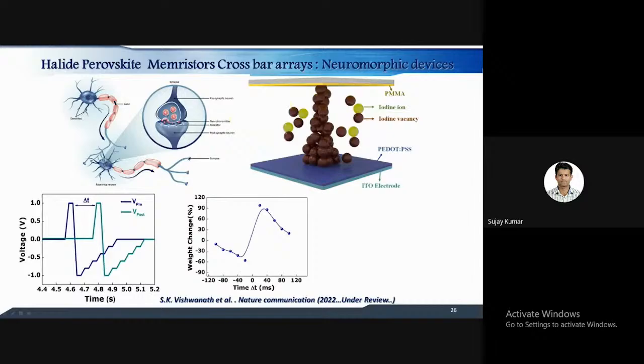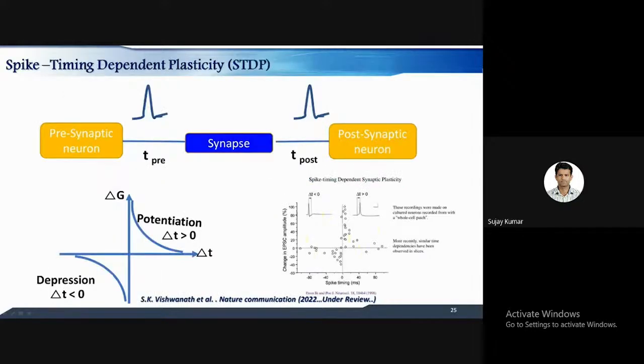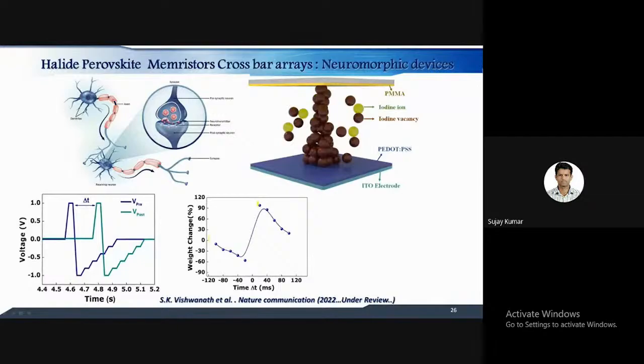What we did is, we assume that the top electrode is a presynaptic neuron and the bottom electrode is a postsynaptic neuron. We applied similar kinds of pulses. You can see here the 1 volt pulse, followed by a negative pulse in a waveform, in such a way as to activate the ion migration in this particular device. So we use different pulses, one on top and another on the bottom. When we apply the pulses before and after, we got potentiation and also depression. The similar fashion we also observed in our devices. That means we are trying to emulate the human brain kind of mechanism through our device.